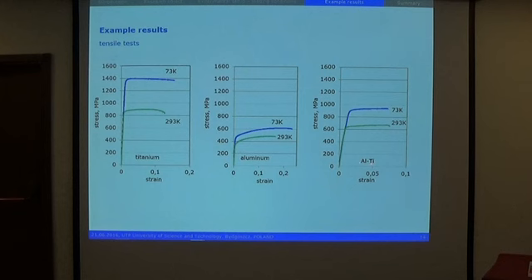Okay, some results. At the beginning, I would like to compare the tensile test made for titanium, aluminum, and our layered material. The biggest differences were for the titanium alloy. For ambient condition, the ultimate stress was about 900 megapascals, but in cryogenic condition it was 1,400 megapascals. It means we have quite a different material here.